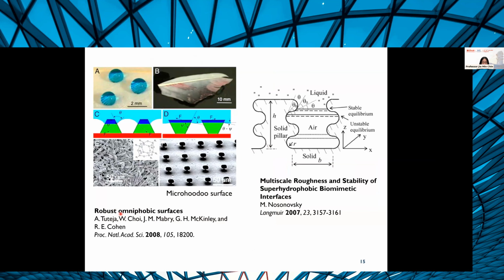And we came across this paper by Bob Cohen at MIT. And their group showed that through a multi-step process of lithography, they could create these micro mushroom-like surfaces. And in these micro mushroom surfaces, they create this special re-entrant texture whereby they are able to repel not just water, but also oils. And this is very much a morphology-dependent repellency.